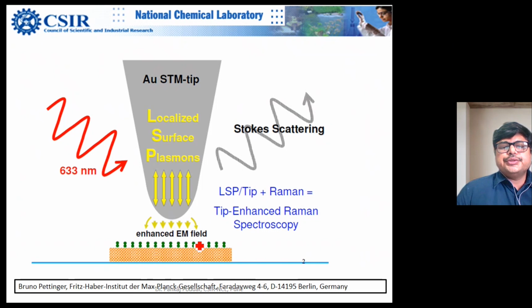So what you can do is get the signal from a few molecules, or for example you are looking for the Raman signal from one particle of, let's say, 50 nanometers. Otherwise it is still a bulk measurement. Even if you use micro Raman, you still get contributions from many particles, or millions of molecules. So tip enhanced Raman is used when you enhance very locally the area which you need.